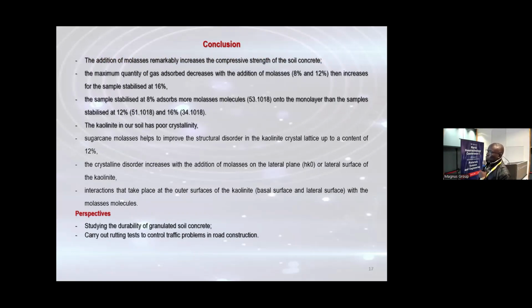The maximum quantity of gas adsorbed decreases with the addition of molasses 8% and 12%, then increases for the sample stabilised at 16%. The sample stabilised at 8% adsorbs more molasses molecules in the monolayer than the sample stabilized at 12%. The kaolinite in our soil has poor crystallinity. Sugarcane molasses helps to improve the structural disorder in the kaolinite crystal at 12%. Interactions take place on the outer surface of the kaolinite with the molasses molecules.